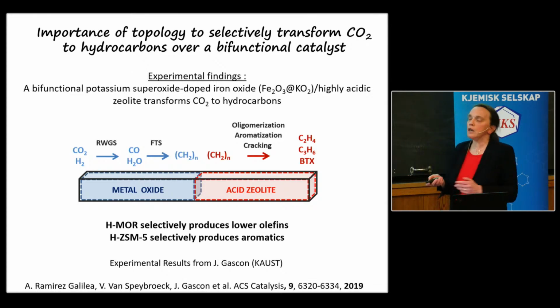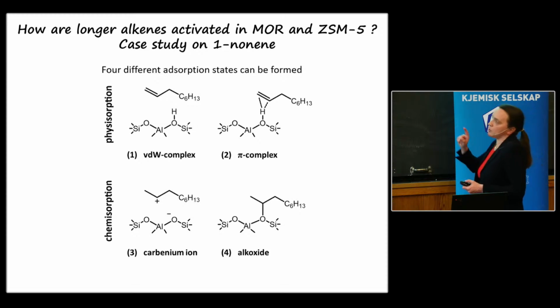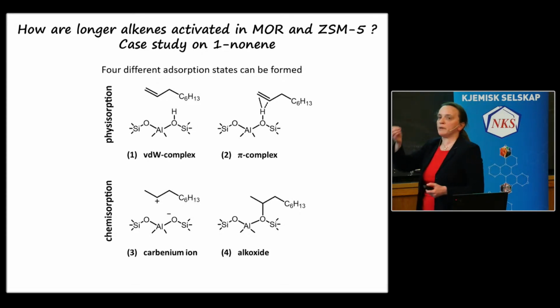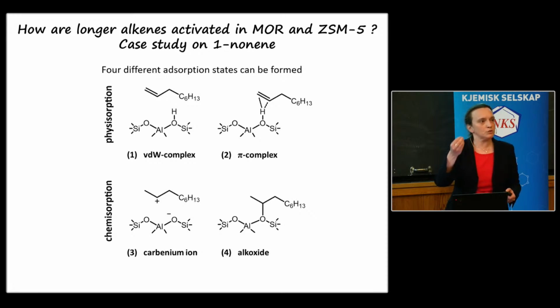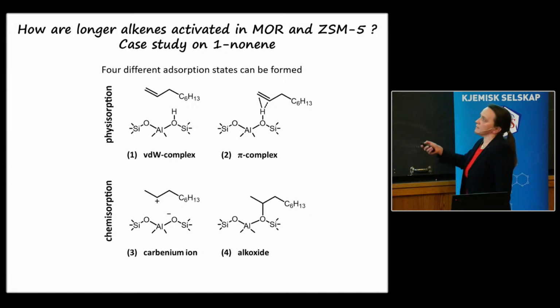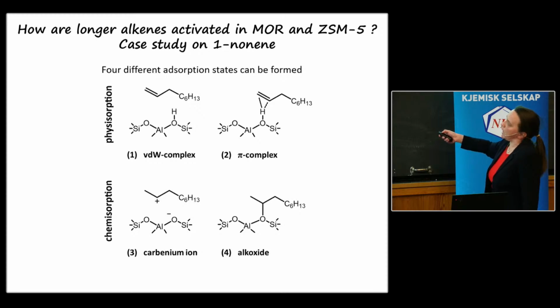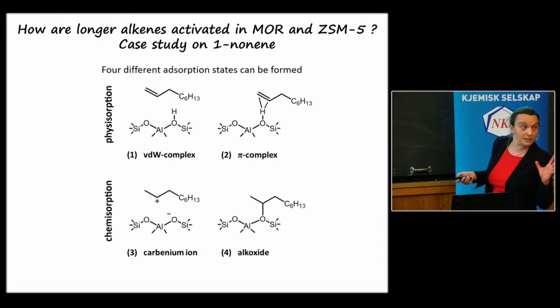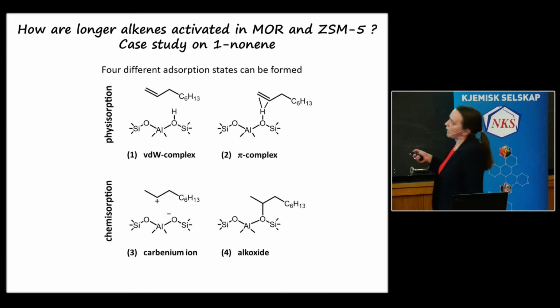It's a very complex story, and that is interesting because I want to point you to the fact that we need to evaluate species at the conditions in which they do the work. So if you look at these larger hydrocarbons, so alkenes, we start there, with nonene that you can see here. When you have nonene and it adsorbs in the zeolite, there are 4 species that can be made. We can have a free van der Waals complex, we can have this pi complex, we can have a carbenium ion, and this is the interesting ion that we need because the carbenium ion will lead to reactivity. And we can also have alkoxide.